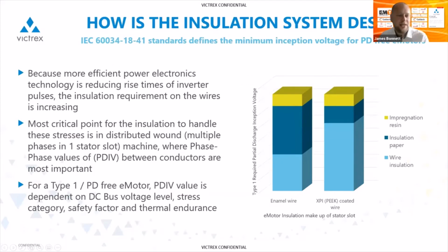So according to the IEC standard referenced in the title, for a type 1 or a partial discharge free electric motor, the calculated PDIV must be done using the DC bus voltage, the designated stress category, the selected safety factor, and then the predicted thermal endurance of the insulation system. These factors are defined by the rise time created by the inverters that govern the size and the frequency of the alternating current sent to the machine. The greater the voltage levels and the rate of switching between positive and negative, the greater the electrical field intensity, and thus the better insulation required.